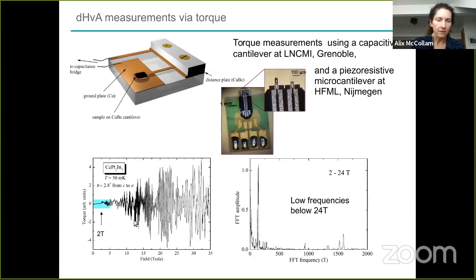So we see very nice de Haas-van Alphen oscillations. This is a magnetic field up to 35 Tesla. This was measured in Grenoble. I failed to write it down anywhere, but this work is actually being led by Ilya Sheikin in Grenoble. And the samples have come from Riku Settai in Niigata in Japan. So this is a collaboration that we're working on very closely, but Ilya especially and his students have been leading this work, and I'm involved a bit. At least we did these measurements here. Well, we've done all of the measurements together.